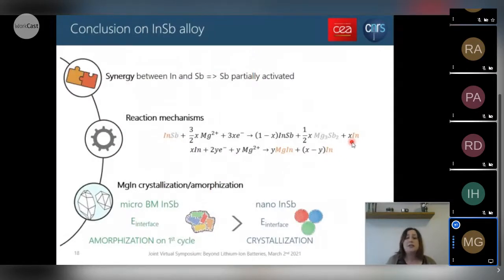So in conclusion on this InSb alloy, we have seen that we've produced a new alloy for magnesium batteries. We show, really remarkably, that there is a great synergy between indium and antimony, which in fact allows us to partially unlock the reversibility of antimony upon reaction with magnesium. We have elucidated the reaction mechanism inside these alloys, and we demonstrated in particular a competition between crystallization and amorphization of this MgIn phase, depending on both the rate and the size of the starting material.